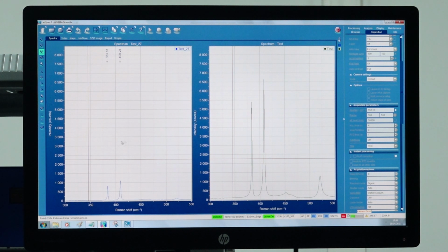So here you can see that the peak intensity for the two Raman signal peaks has increased, and we saw the last time that for the bulk signal it had a lower intensity. These kinds of changes in intensity, changes in relative intensity, changes in the peak positions help us to determine the properties of the material that we are investigating. Here you can again observe that the silicon peak has a larger intensity. This is because the flake that we had chosen was thin. Therefore, Raman signal could be obtained even from the silicon sample beneath it.